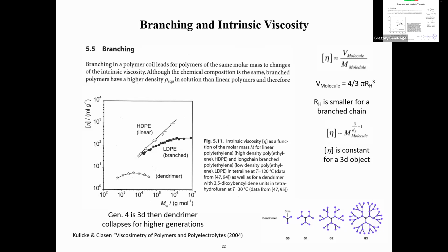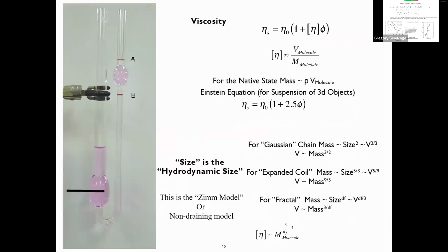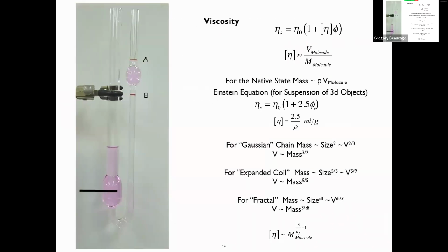But anyway, last time on the tape I went through intrinsic viscosity. Basically you end up with an equation where the intrinsic viscosity goes with mass to some power and then a prefactor. Those are called the Mark-Houwink coefficients, and you can look them up in the Polymer Handbook. That's the main source for those. You can look up every polymer, but those coefficients will change with the solvent and the temperature, so there'll be different numbers for each solvent and temperature.